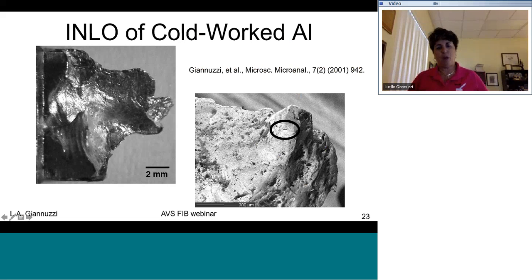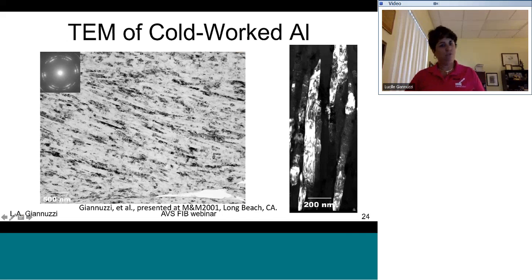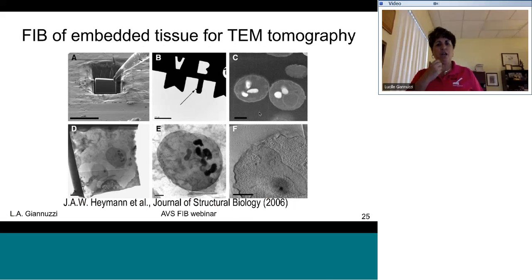Here's an example of why lift out in general is so useful. You can put in a chunk of material. This is cold worked aluminum. So without having to cut this up or destroy the fracture surface, you can just drive out to any location at the end of the tip. This is out here. Make a sample, pop it in the TEM, and now you've got your cold work structure that you can analyze and texture structure. Okay. You can also apply this to FIB embedded tissue for TEM tomography, not a problem. Lift it out the same way, make your TEM sample, and you can do tomography on this sample.